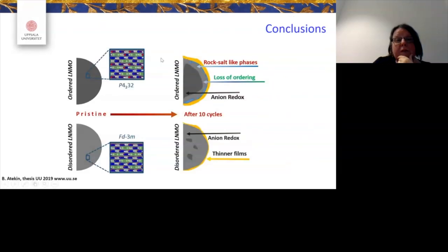And by doing some experiments on the surface, especially HAXPES that we did in Berlin at BESSY, we could see that it was not only that we had this rock salt-like phase for the ordered one, we also got a lot of surface species and build-up of an interface, which was rather thick, to the electrolyte. And if you have the disordered one, you can see that you had this anion reaction all through, but you never really got this rock salt-like phase. And you also got a very much thinner film of this material.